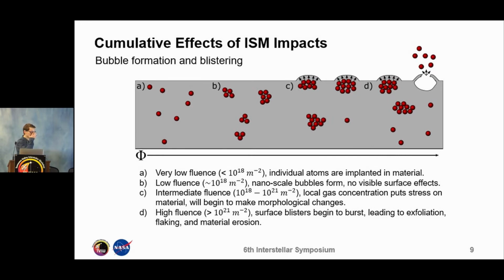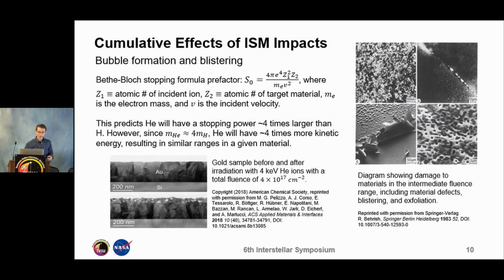So we can discuss bubble formation further. If we just consider Bethe-Bloch stopping, so just electronic stopping, you get this prefactor in front of the Bethe-Bloch stopping formula where Z1 is the atomic number of the incident ion and Z2 is the atomic number of the target material. This predicts that helium will have a stopping power approximately 4 times larger than hydrogen. However, since the mass of helium is approximately 4 times the mass of hydrogen, helium will have approximately 4 times more kinetic energy and thus will implant at a similar range as hydrogen.